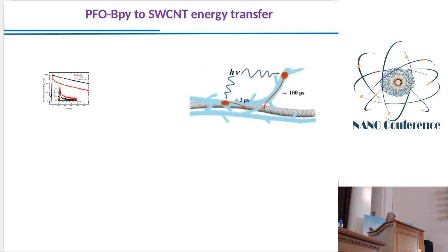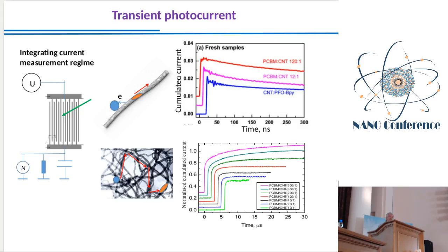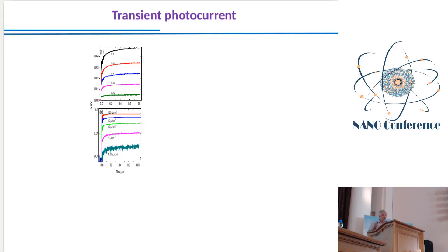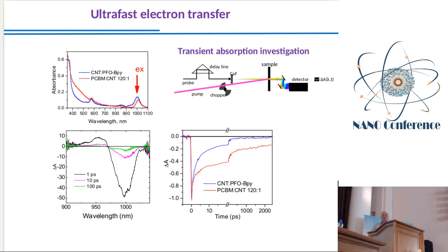Here are transient absorption measurements, which I had no time to discuss, but here we observe also charge carrier separation. Without PCBM, we have just exciton decay, and with PCBM, we have long-lasting transient absorption, which shows that indeed charge separation takes place, and charge separation takes place on carbon nanotubes because we have bleaching of the carbon nanotube band.